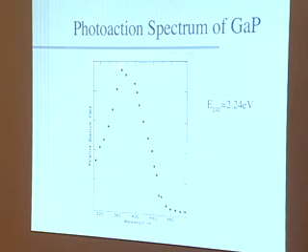And it should go up, and it should not come down. This is due to another absorption out in solution in this particular cell that I'm using. So this should just go up. Once I hit the band edge, I have lots of charge carriers and a real depth of orbitals, and so it's not going to come back down. It's just going to go out. And from this onset, I can determine things like this band gap of 2.24 electron volts for the gallium phosphide interface.